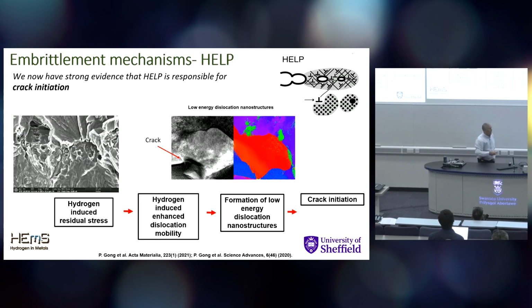I'll skip that one. So what about the mechanisms? Does this agree with all these predictions and so on? So actually at this initiation site here, with the region of low dislocation density, you can just see a crack in there associated with that boundary with a high dislocation density.